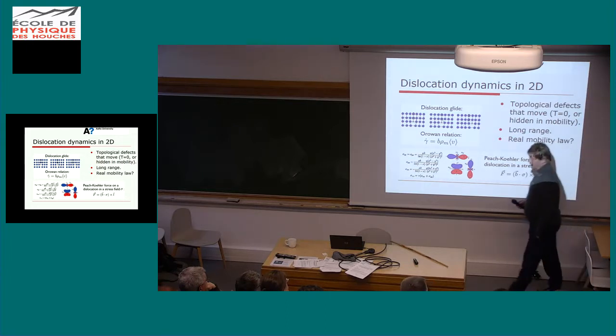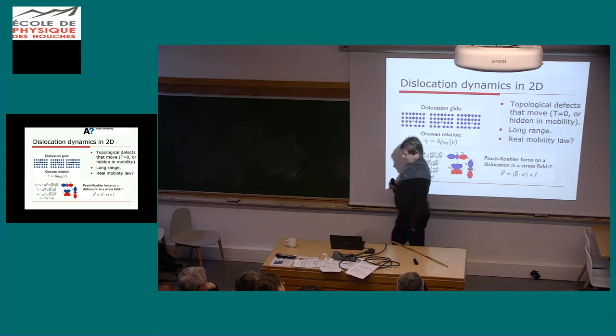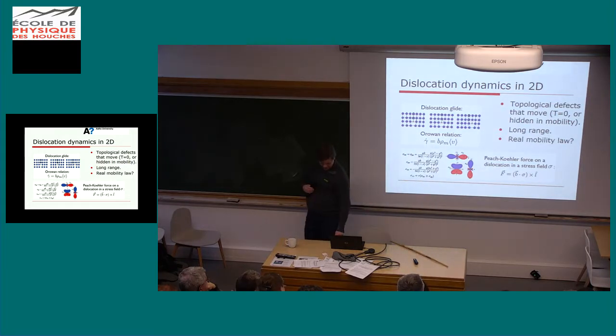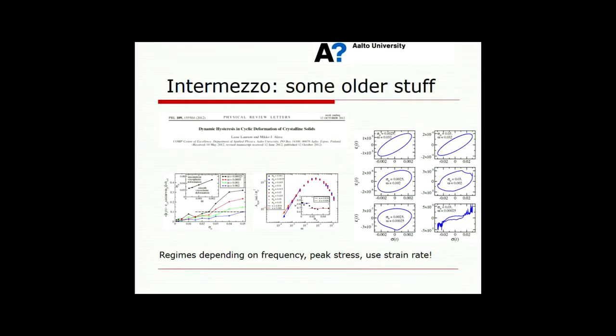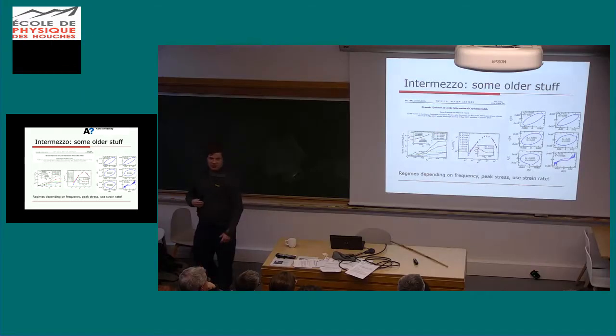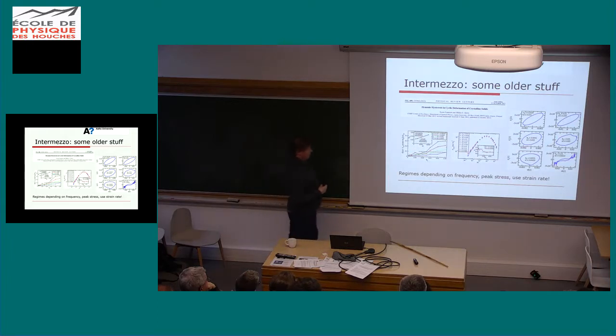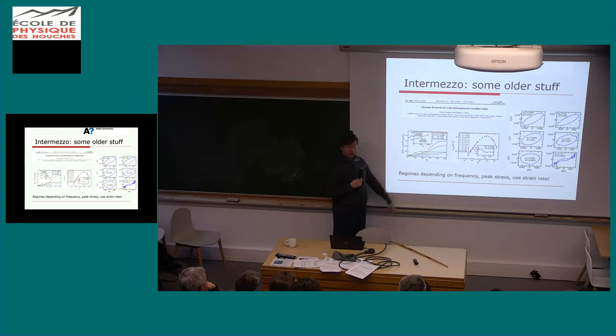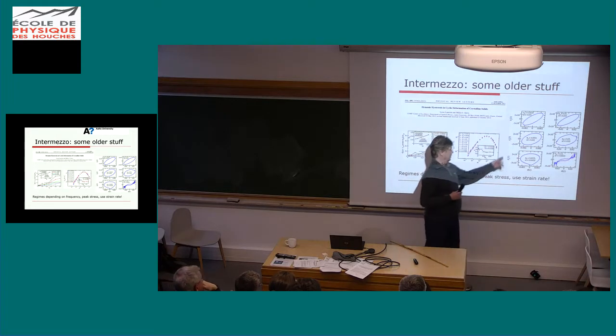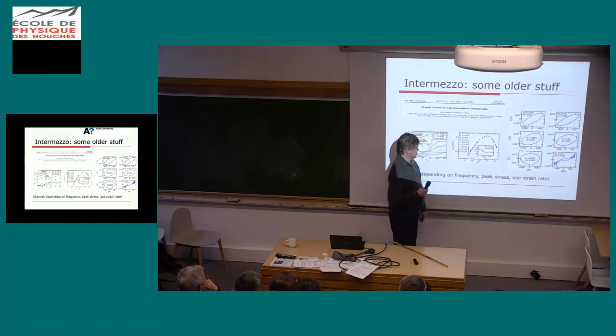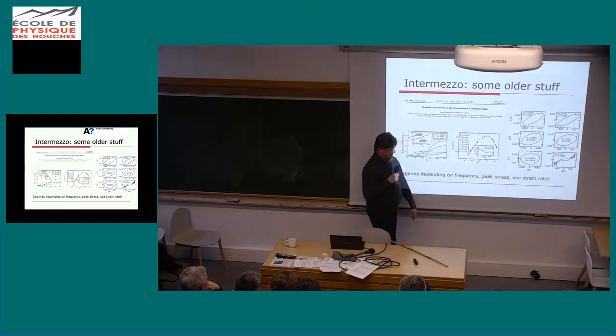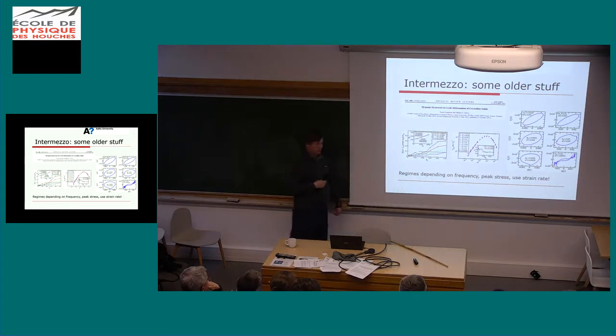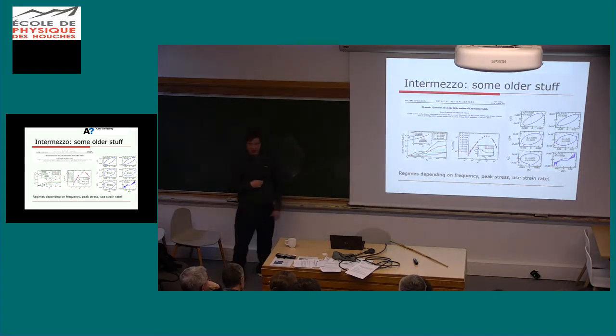But that's how you can test these things if you just want to do this in reduced dimensionality. So, because people thought, I've been talking ad infinitum about the case of amorphous plasticity and what you learn if you do large amplitude oscillations. I cannot yet avoid pointing out this paper that we did a long time ago where we did the same things. You have Lissajous plots, and what you figure out from the amplitude of the hysteresis loop and how that scales as a function of the stress that you apply and the frequency of the external stress, and you get all kinds of interesting results.